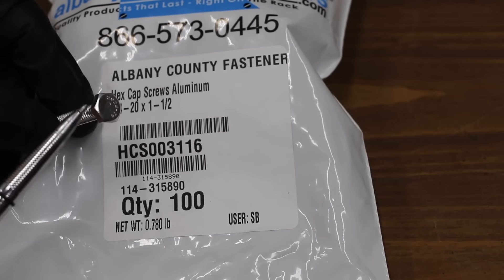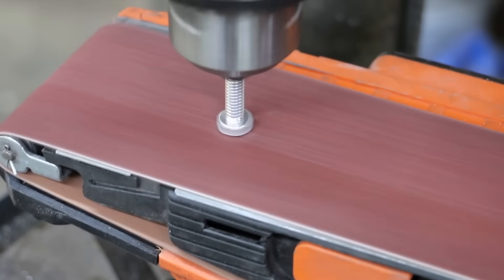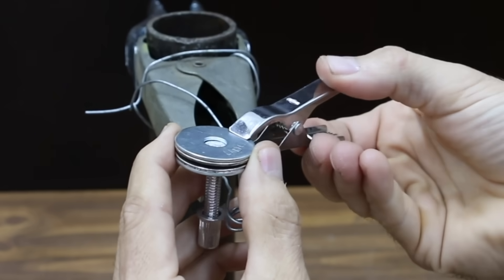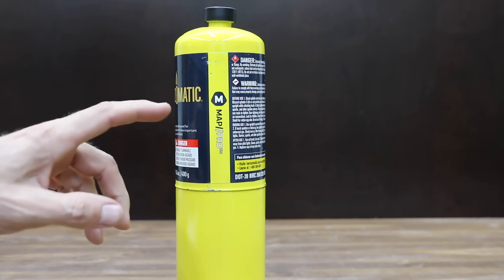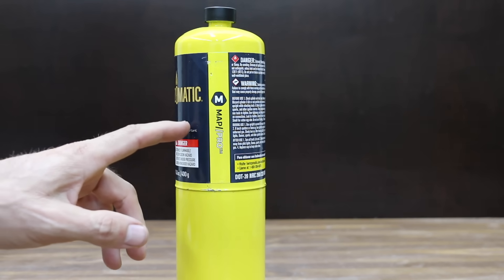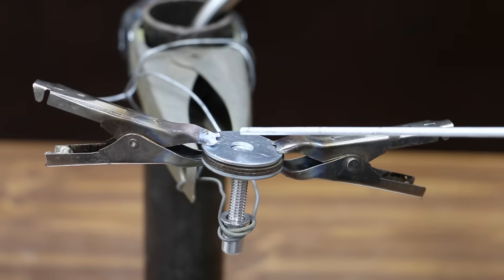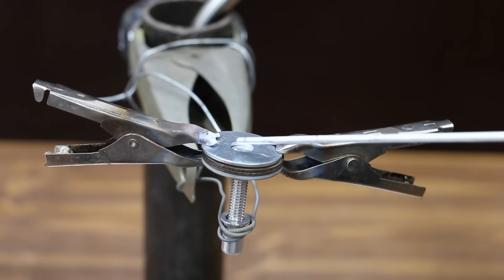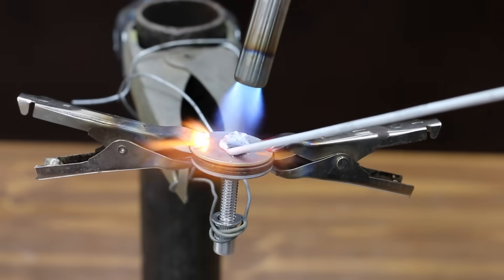For the next test, I'll be plug welding some 5/16 inch washers to some 1/4 inch hex nut aluminum bolts in order to measure the tensile strength of each product. I'm going to first sand down the head of each bolt using a drill press and a belt sander to remove any oxidation and to create a uniform abraded surface. I'll clean each of the test pieces with some non-chlorinated brake parts cleaner. The extra washers will serve as spacers. We don't want the weld to stick to the washers, only the bolt. Propane will work fine, but I'll be using some map gas, which will heat up the metal much faster. To keep from melting or weakening the shaft of the aluminum bolt, I'll be pouring heat into the top of the metal washer and the head of the bolt. I'll be using a Blue Demon welding rod to improperly use this welding rod. What I'm going to do is actually heat up the welding rod itself instead of the metal, and we'll see how much strength we get. I'm leaving a lot of weld overlap on this plug weld to serve as a fastener, since the low temperature welding rods won't stick to the ferrous metal.